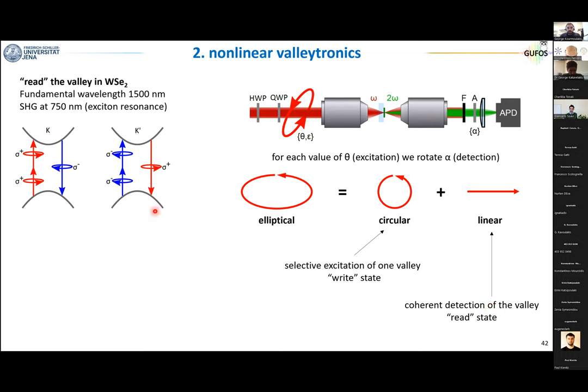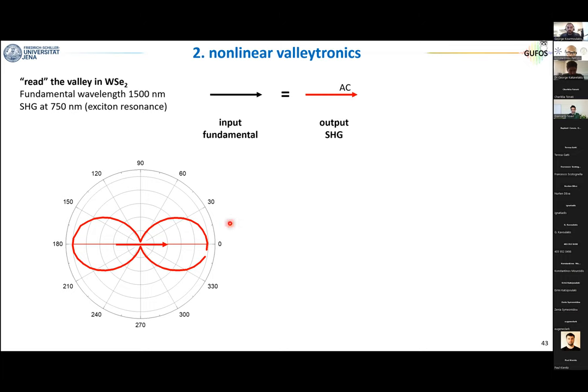We go on WSe2 and we shine elliptically polarized light. Now, this elliptical polarization is the perfect superposition between a circular component that breaks time reversal symmetry, so generates the valley imbalance, and a linear component that we use to read the valley polarization. And here are the experiments. Let's say that we start from a linear case. The input is linear, polarized along the armchair direction. So this is a polar plot. Zero is the armchair direction. The output, the red curve, is again linear, as you can see, polarized along armchair.